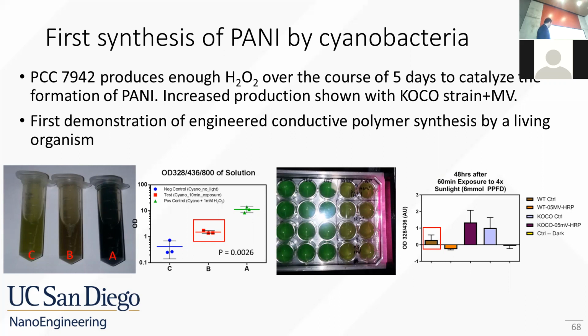This is a negative control sample where it was not exposed to light, it was just left in the dark. And then sample A was a positive control sample where hydrogen peroxide was added extracellularly. Furthermore, if you use the KOCO cells and electron transport chain inhibitors, we can see a 200 to 300% increase in the production of polyaniline just in response to light.